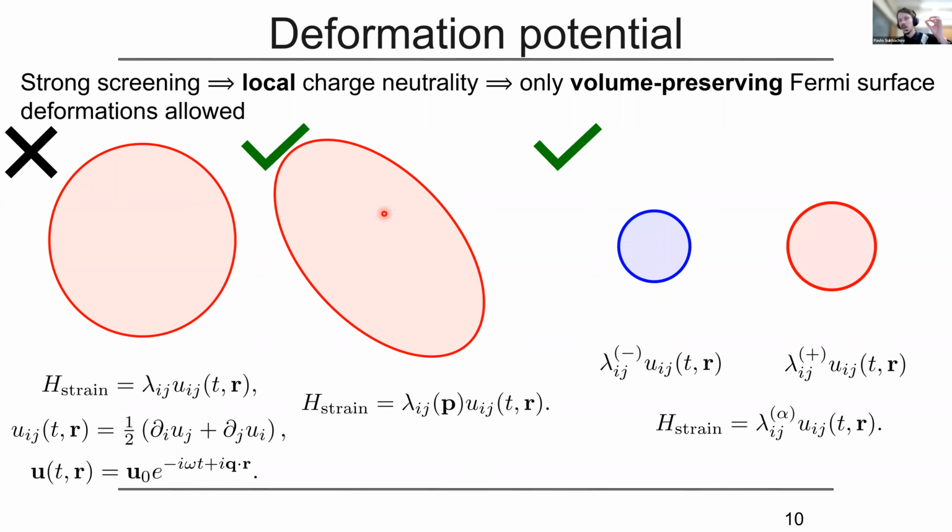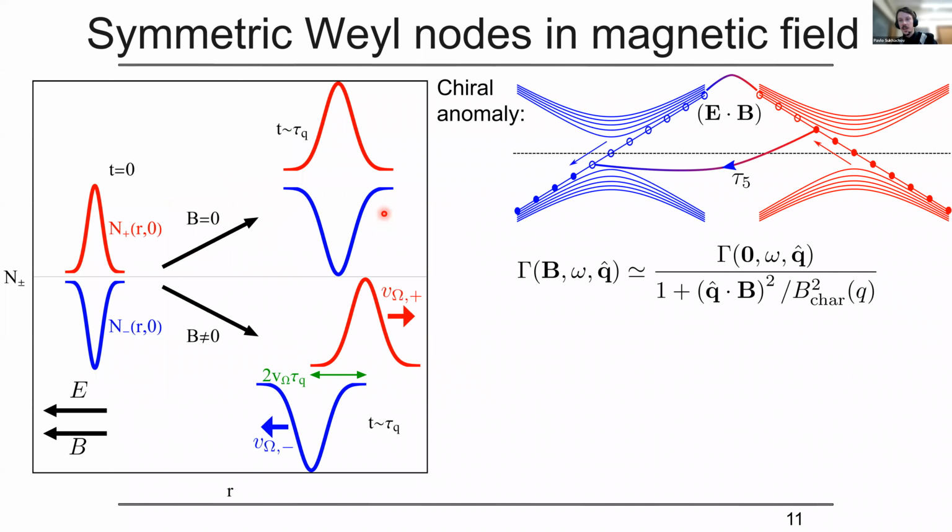That's why I do have this large charge, and that's why I have the screening. If we have Weyl points exactly at the Fermi level, then screening becomes less relevant for this chiral anomaly, and this result would be modified. So just to reiterate, this result assumed that the Fermi level is rather far from the Weyl nodes. So we have a Weyl metal rather than a semimetal here.